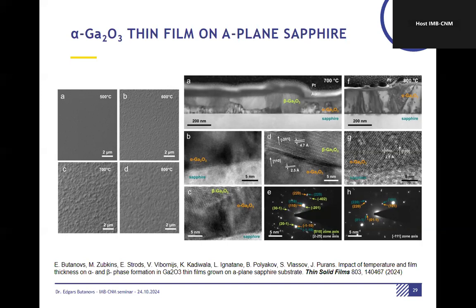This is A plane sapphire. It's not the best, but there are some completely new results. On M plane sapphire, I think we can grow up to 600, 700 nanometers, which is close to the state of the art of what I've seen in the literature on the thickness of alpha phase layers, except mist CVD, I would say, but I'm not sure if I've seen very thick films. So it's quite an interesting result, and we want to see what we can do with these alpha phase films.